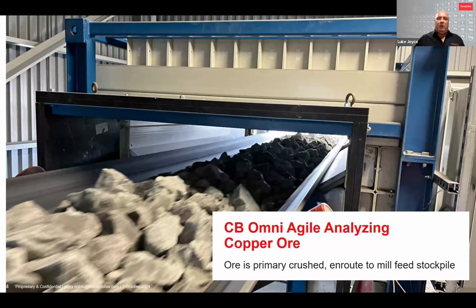So here we have a photo of the installed CB Omni at Red Chris, and as you can see, it's measuring run-of-mine feed with the neutrons and gamma rays fully penetrating these rocks to enable real-time analysis of the entire material flow. The reference standards shown in the previous slide were measured during the factory calibration and then shipped to site with this analyzer, and we measured them on site during the commissioning to validate the performance that we achieved in the factory.